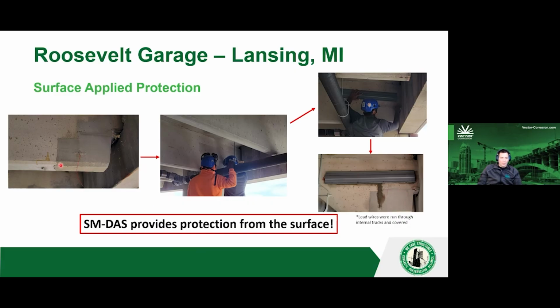So the contractor went ahead and repaired the areas that needed it. And in the repair, while it was open, they made their electrical connection. They touched all the wires, made it a durable connection, ran that lead wire out, and then they could come afterwards, do some surface prep, install this surface-mounted DAS anode, and this is kind of what the final product looks like. You have this socket protecting that lead wire. It runs up into this little conduit area built into the anode, and this will actually be protected as it's run over to the end, and there's end caps to make sure it's not a weak point. It's actually going to be a durable solution.